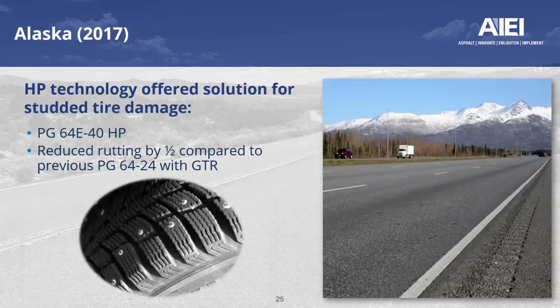Going up to Alaska, HP offered a solution for studded tire damage, and the typical binder used in that state when it's labeled HP is a PG64E-40. It reduced rutting by almost half compared to the previous binder, using other alternatives.